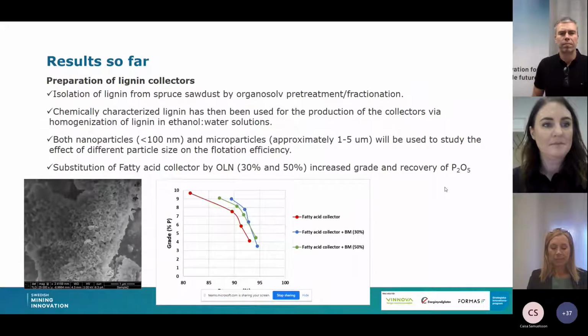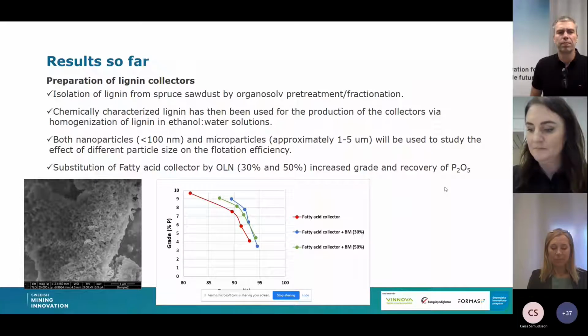So far, we isolated lignin from spruce sawdust by organosolv pretreatment. The chemically characterized lignin has been used for production of the collector via homogenization of lignin in ethanol water solution. Both nanoparticles and microparticles will be used in the study. So far, our results suggest that substitution of fatty acid collector by lignin increased grade and recovery of phosphate.